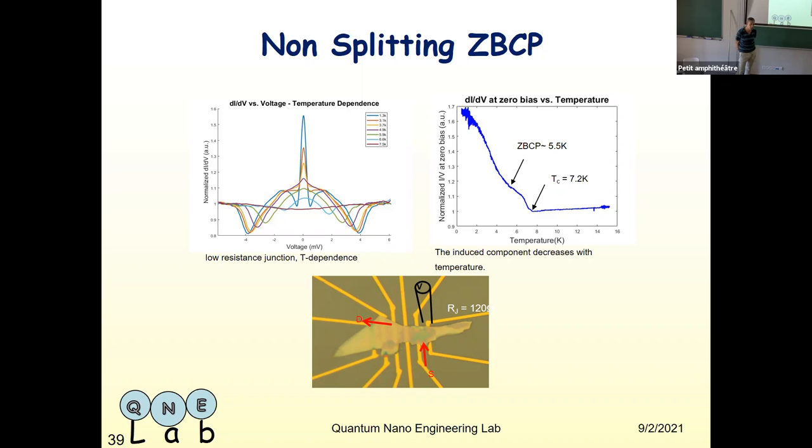Okay, so it is quite likely that you do not see the superconductor directly, but you see the proximity effect in the chiral molecule. It's a proximity effect. Yeah, okay. But we do know that if you put on a very thin layer on the other side, we do see the effect, which penetrates to the superconductor. I will show a proof of that. But it's some kind of proximity effect. We also have a measurement on gold. We added the gold and then put the chiral molecule, and we did see again this peak in the density of states. So it's a real proximity effect, but it's some kind of a system.